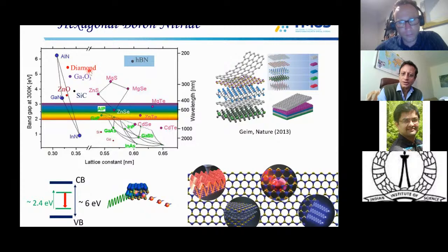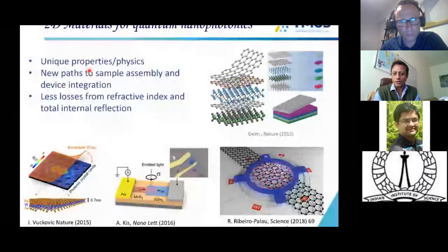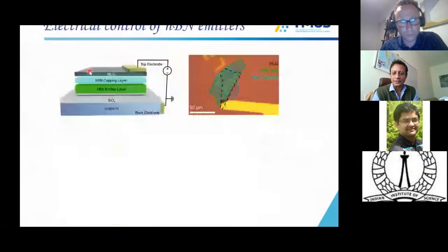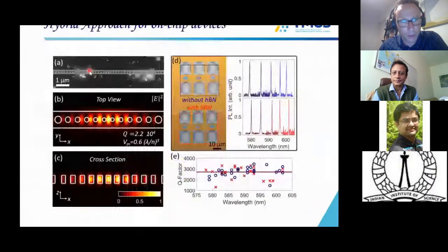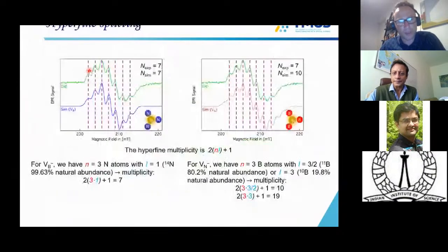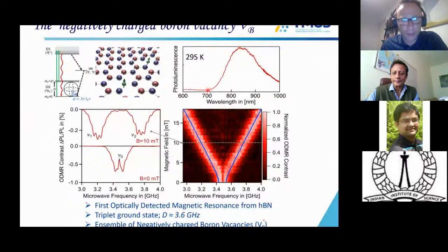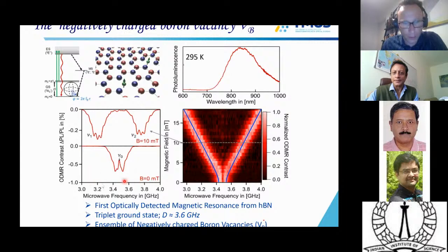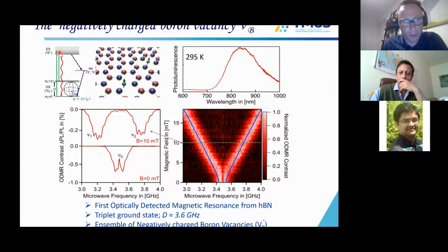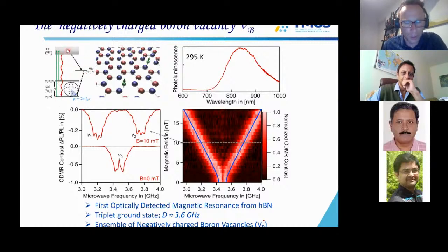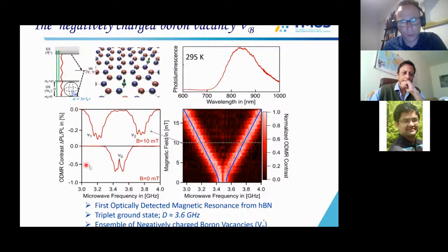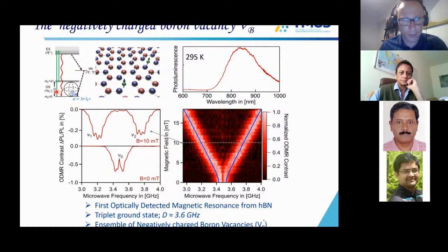Okay. The next question is, will you explain the spin defect once more, and how is it connected to the bullseye cavity? This is also another question from Amit. Yeah, sorry, maybe I was racing through it, so let me spend a bit more time on it. Basically, spin defects are defects where you can record your luminescence, and when you apply your microwave frequency, you can see a dip in luminescence. This is because as you excite your system, it can go through the metastable state or directly down to the ground state. One of these transitions is spin forbidden and one is spin allowed. Because they have different rates, you will see a contrast in what's called ODMR. The reason this is important is that it's a spin-dependent transition, very sensitive to anything spin related, which is magnetic or electric field. This is why this type of system is very important.